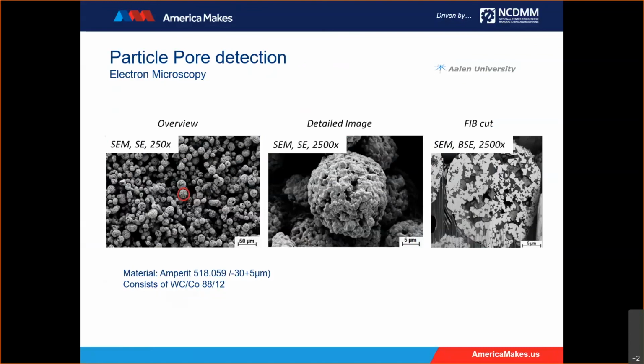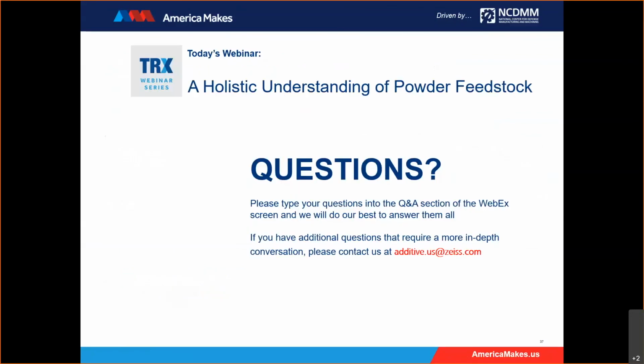On the left-hand side here, you can see the powder that's spread. In the middle, you can see an image of a tungsten carbide cobalt powder. And on the right, you can see where we've sectioned the powder particle to visualize this porosity. This is typically used for research projects when you're trying to develop a new alloy and you want to see how well it's going. So that's definitely an option that's available to you.